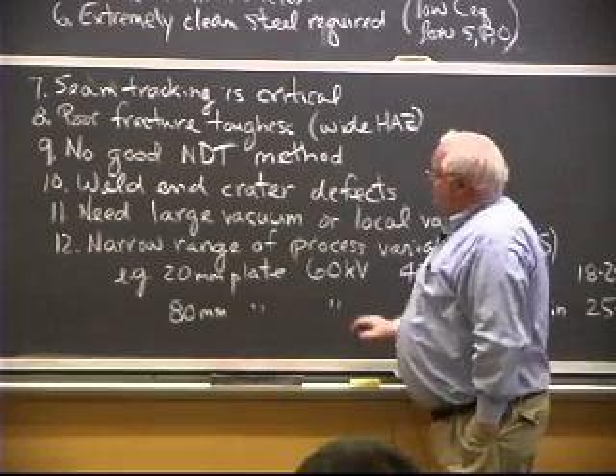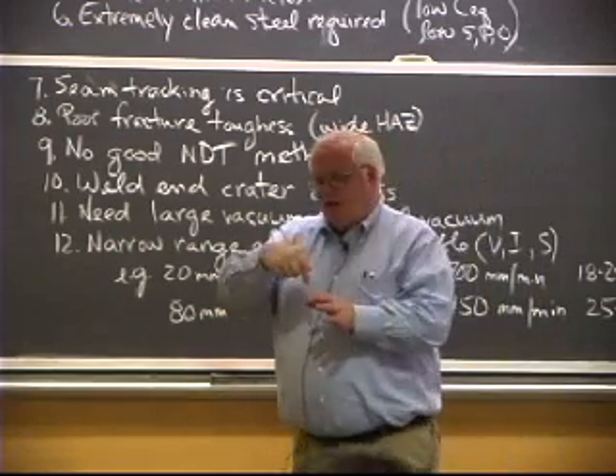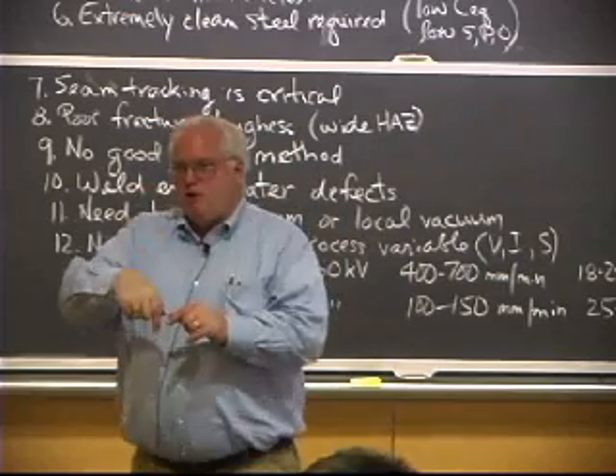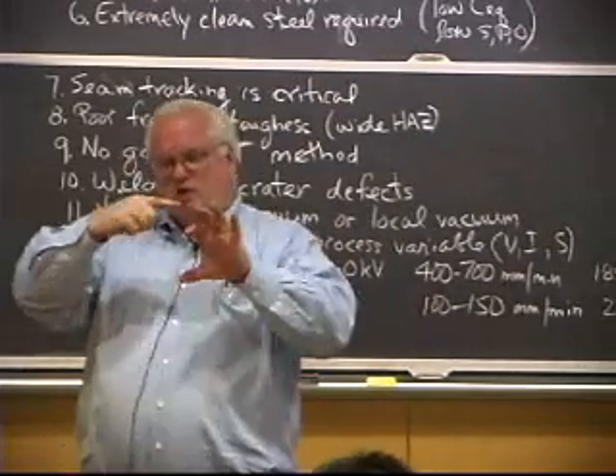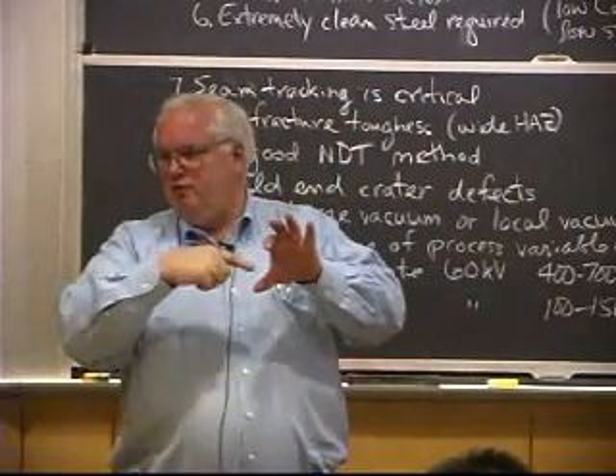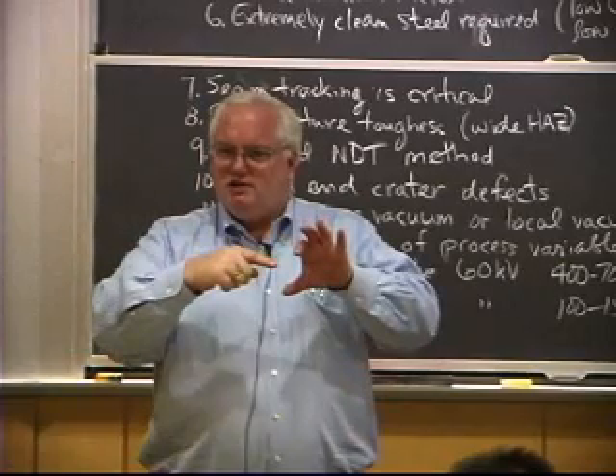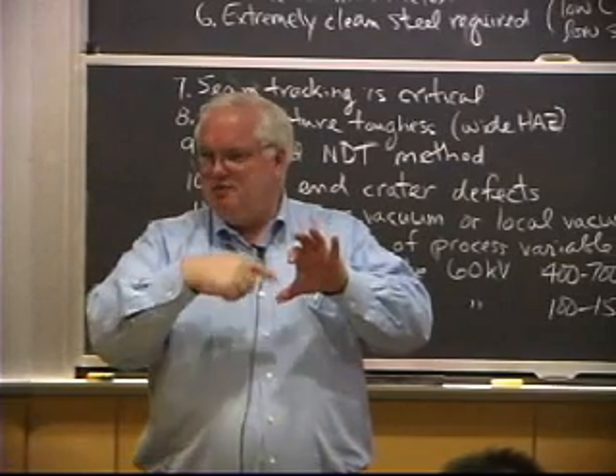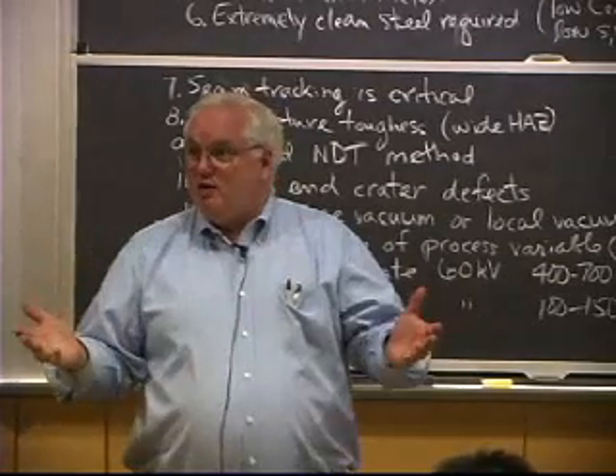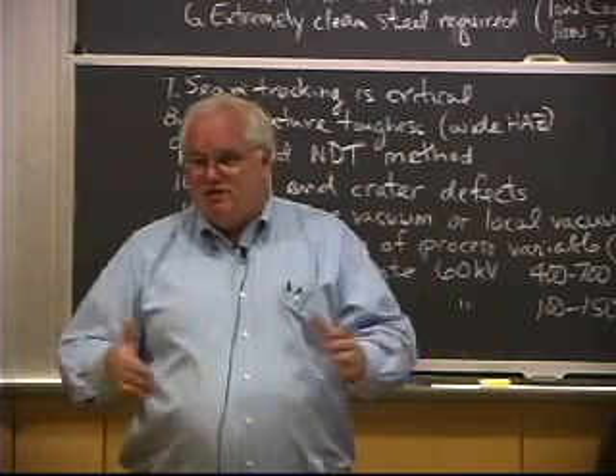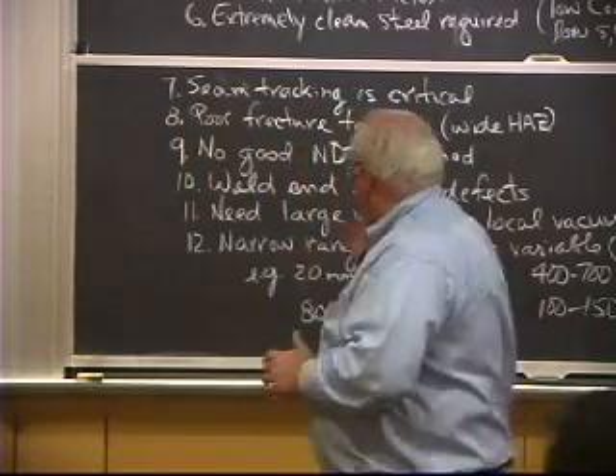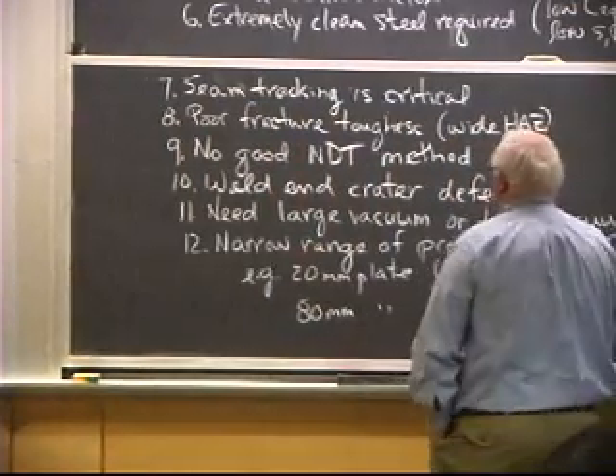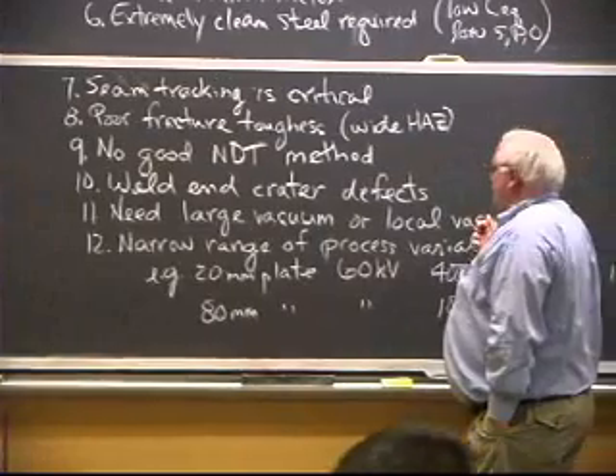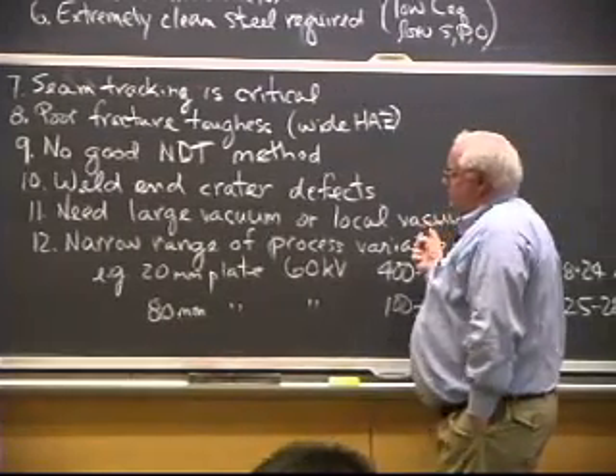Weld crater defects. This spiking phenomenon gets worse and worse if you're doing a partial penetration weld. Well, when you're going all the way around the seam, you're doing a full penetration weld until you get to tie it in at the end of the circular weld. Now you're welding partial penetration, and you always produce defects. So crater defects were a problem. You need a large vacuum or a local vacuum, which adds to the cost.